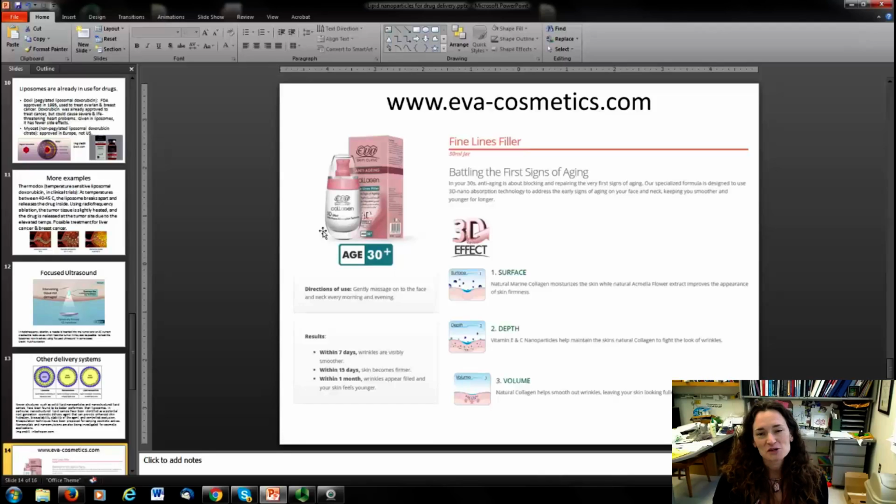What do you think? There are some on the market right now that are using these kinds of nanoparticles to encapsulate vitamins like retinol, vitamin A, vitamin E, and C, and then you rub it in the skin cream. It gets taken up and released and has been shown to be good. Retinol, for example, has a tendency to break down or degrade. It has a short shelf life because if you expose it to ultraviolet light from sunlight or whatever, it'll break down. And so if you encapsulate it in the liposome or some sort of nanoparticle, then it's protected and it doesn't break down as quickly, which increases the shelf life of the retinol. And of course, retinol has been shown to fight wrinkles and aging.